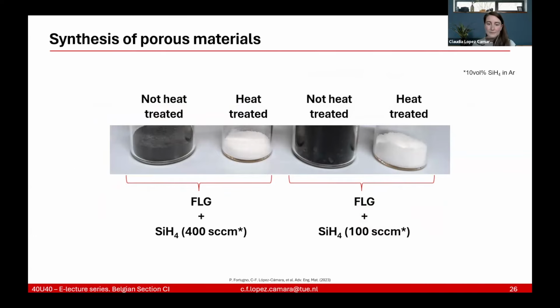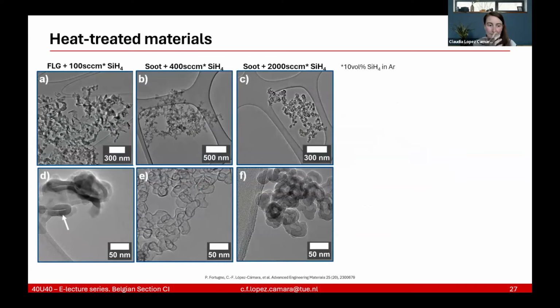The only difference between the samples, apart from the heat treatment, is that in one we used less silane and in the other more. So we have more silane and therefore more silica at the end, and the other one we use less. So we looked into what this powder actually was, and we found out that we were creating a new template method. Using few layer graphene, which is the first column of pictures, picture A and picture D, we have graphene, but after we heat it up in picture D, we see that there is only silica left. We basically covered all the graphene in silica, and the graphene that was inside the silica got burned after we heated it up.